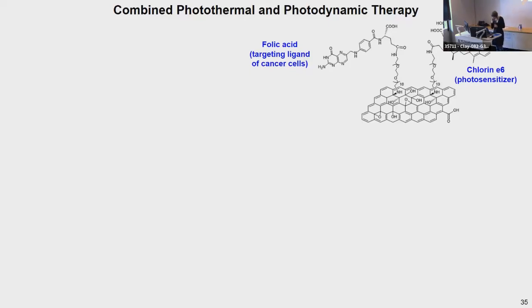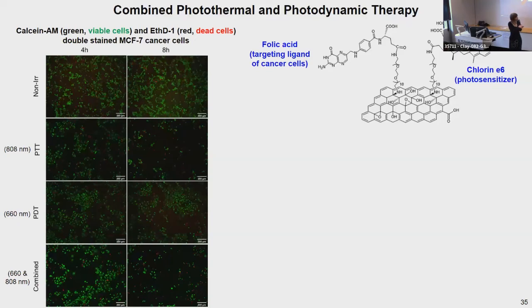We incubated the double functionalized graphene oxide with cancer cells for two different incubation times. In green, you can see viable cells, stained with a specific dye, and in red, the dead cells. These are the cells incubated with the double functionalized graphene oxide without any light irradiation. So we see many viable cells. When we performed the single treatment, photothermal therapy, by irradiating the cells with a laser at 808 nanometers, you can see much fewer cells and also some dead cells.